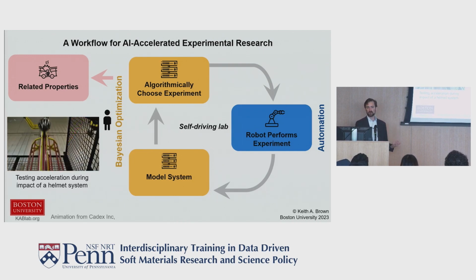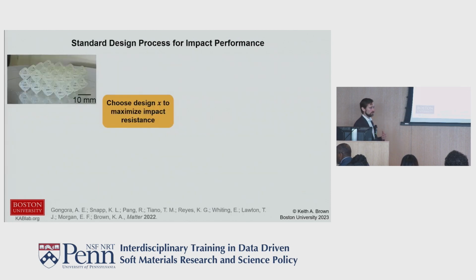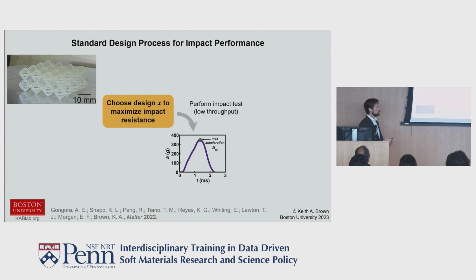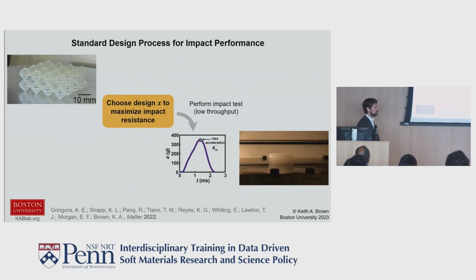The way this is typically done currently is an iterative process. To study that process, we developed a set of generalized lattices. These are also 3D printed, but we're using a stereolithography process rather than fused filament right now. What we typically would do is choose a design we think is good, and test it. This is what the result of the test is: an acceleration versus time plot. Typically, what you care about is the highest value of the acceleration. This is when the damage would be done.